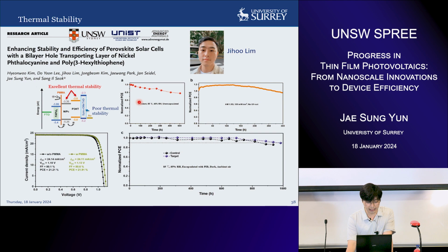So they tested this material under 40% humidity and 85 degrees without encapsulation, and you can see that it still has very high stability, and under illumination as well. And under 85 degrees, 85% humidity, when it's encapsulated, it can be maintained for 1,000 hours with only around 20% loss of efficiency.